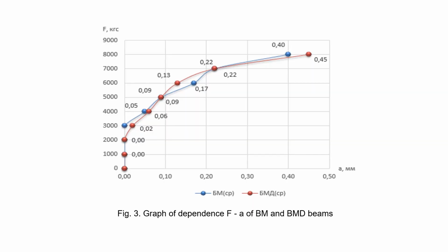Fig. 3-5 shows the graphs of the load, crack opening width dependence separately for the series with the same reinforcement. The tendency to increase the width of the normal crack opening of beams under load made of concrete on fine tailings waste shows almost comparable results with the series of beams made of concrete on quartz sand. The overall performance of the beams of all series depends on the type of reinforcement used in the tensile zone. Beams reinforced with metal, BM and BMD series, showed typical performance as for beams with traditional reinforcement.